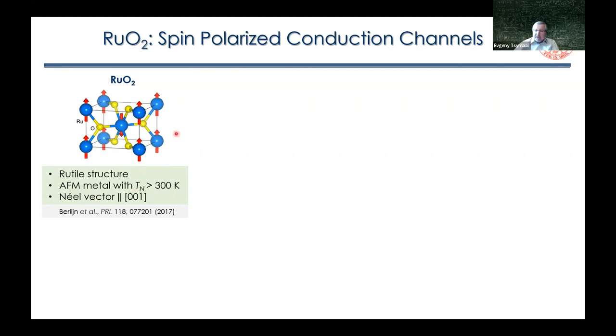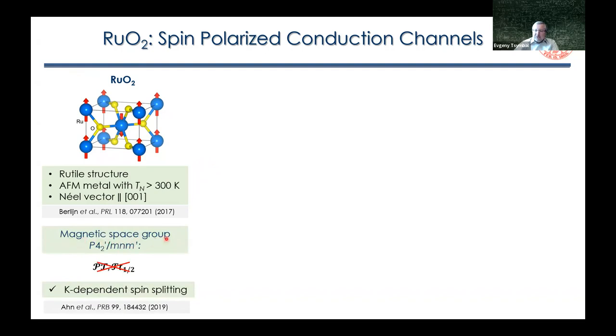It has magnetic type A antiferromagnetic ordering, where we have 001 planes with ferromagnetic alignment of magnetic moments. But if you go from one plane to the next plane, the magnetic moments are aligned anti-parallel. So the Néel vector is pointing along the 001 direction, as shown here. So what is important is that the magnetic space group symmetry is such that it breaks both PT and T-tau-one-half symmetries.